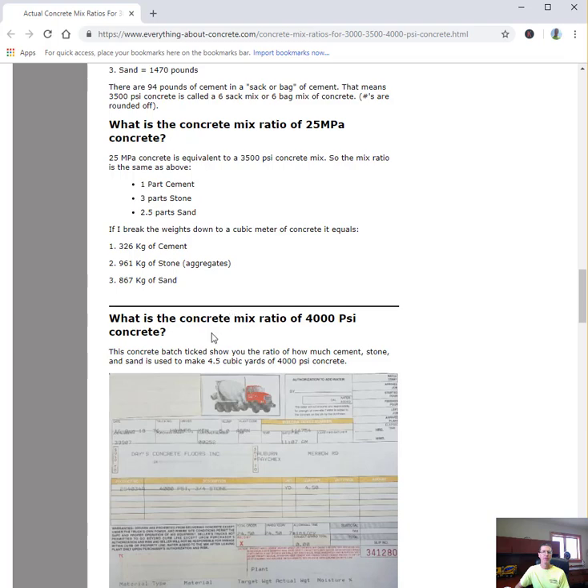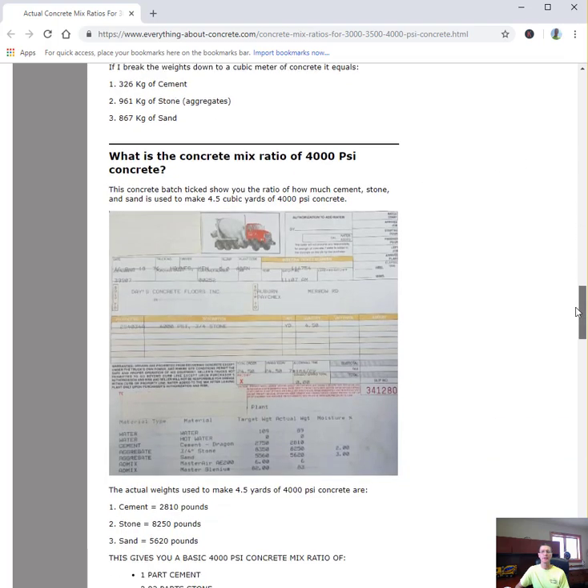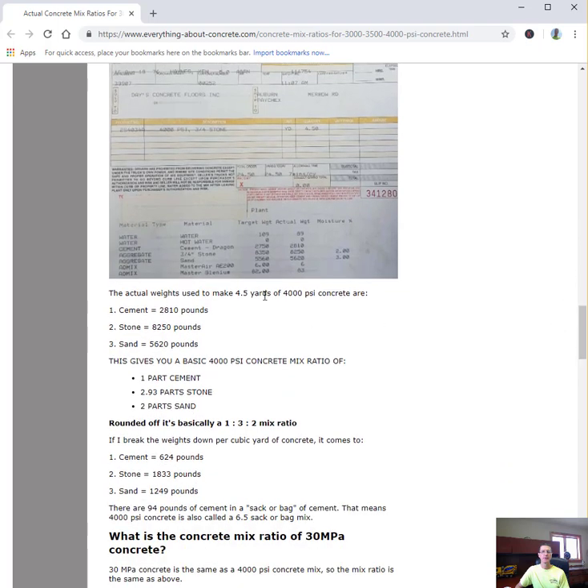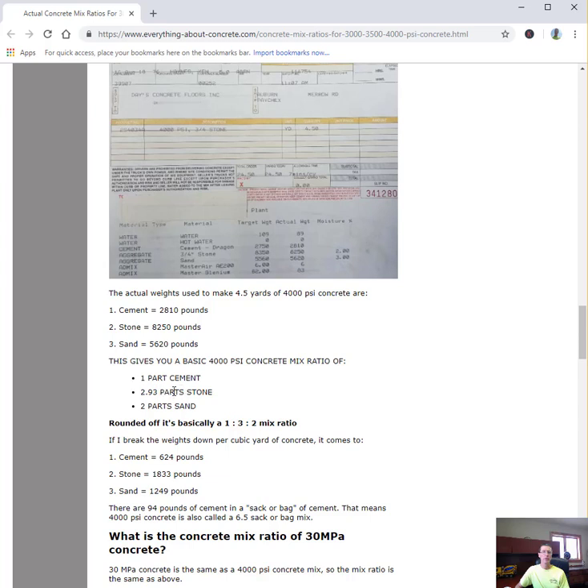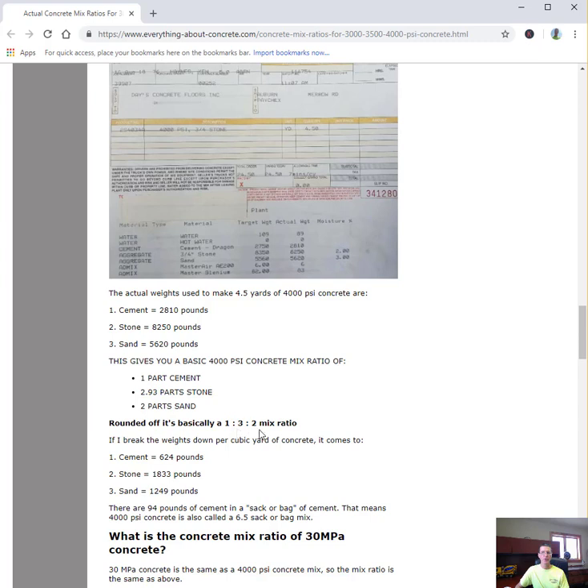Now a 4000 PSI mix, which is even stronger concrete. This ticket was for 4.5 yards with 2,810 pounds of cement, 8,250 pounds of stone, and 5,620 pounds of sand. That comes out to 1 part cement to 2.93 parts stone to only 2 parts sand - a 1 to 3 to 2 mix ratio if you're mixing this by hand. If you had the plain ingredients on the ground, you could take 1 shovel full of cement, 3 shovel fulls of stone, and 2 shovel fulls of sand, and you'd be pretty close to a 4000 PSI mix ratio if all the shovel fulls were the same.